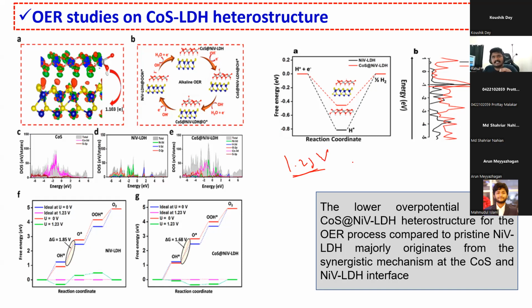Because there is some kind of overpotential or some kind of barrier we have to cross to split the water. So in order to reduce that value, we are actually working on catalysts for reducing the overpotential to split the water at a much faster rate. So for this study, we used a cobalt sulfide nickel vanadium layered double hydroxide heterostructure. We made a heterostructure, and this is the charge density difference plot.